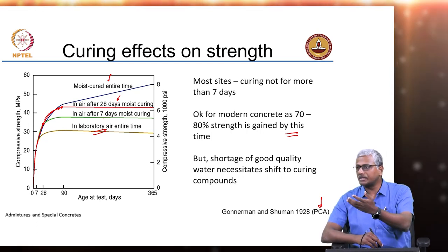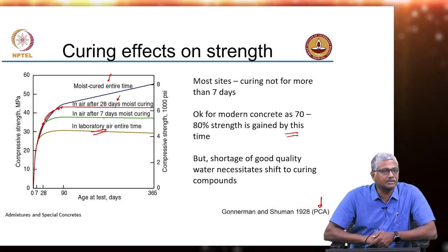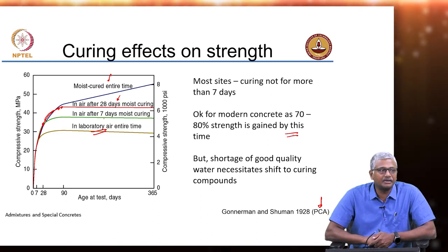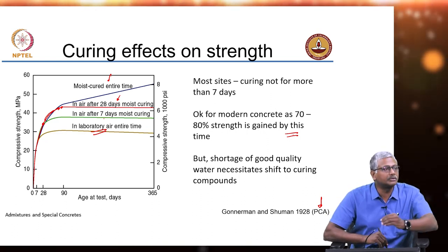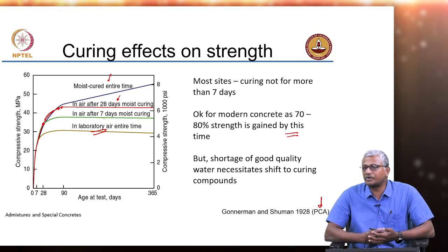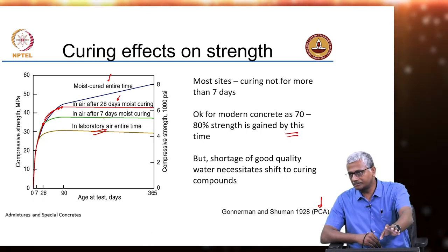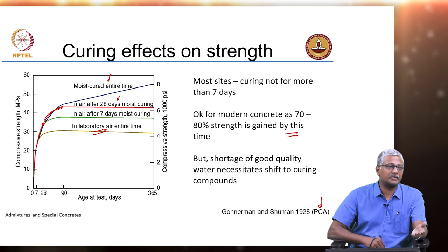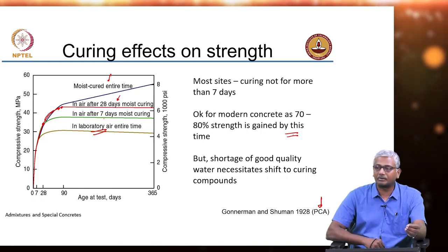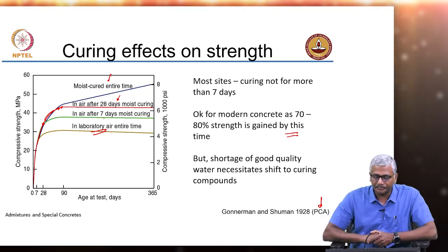The problem is when you start using mineral additives like fly ash, which slow down the reaction — your strength gain may not be achieved up to 70 percent within 7 days. So you may have to prolong the curing by a few days, and that is very important for an engineer to understand because it is affecting your productivity and economy. But the investment of this longer-term curing for mineral additives-based concrete is going to extend your service life significantly.